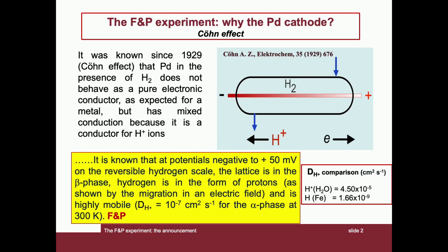For comparison, the diffusion coefficients of the proton at 25 degrees C in liquid water and that of the hydrogen atom in iron in the solid state are reported. The difference in order of magnitude illustrates the peculiarity of the hydrogen-palladium system.